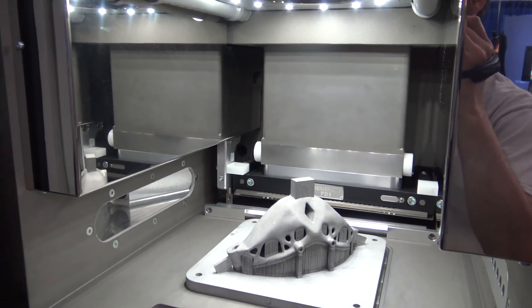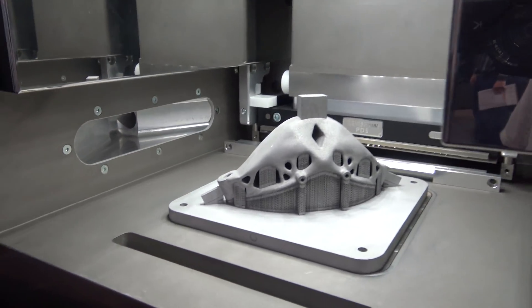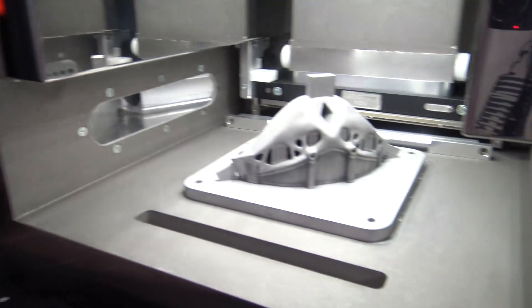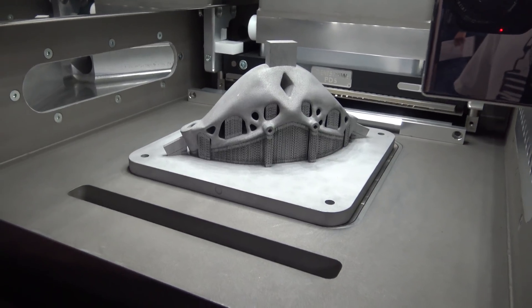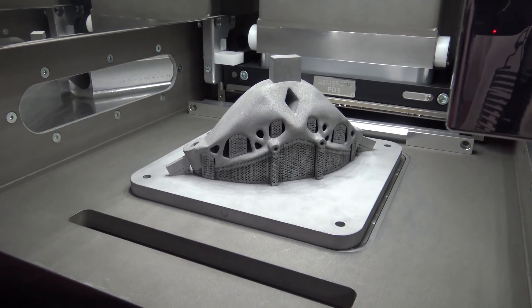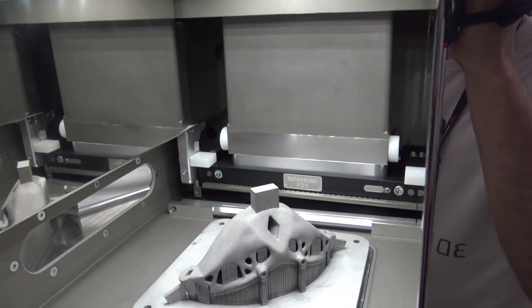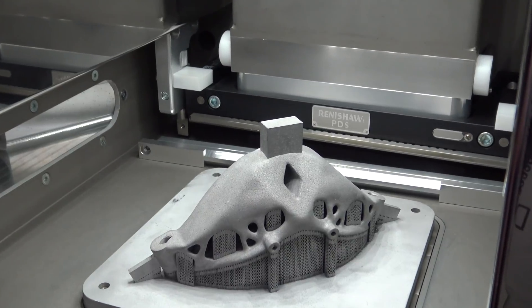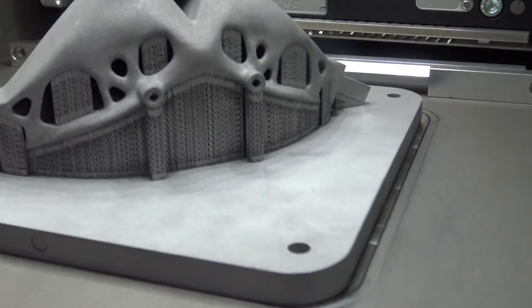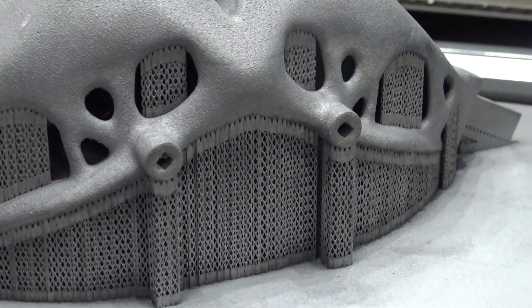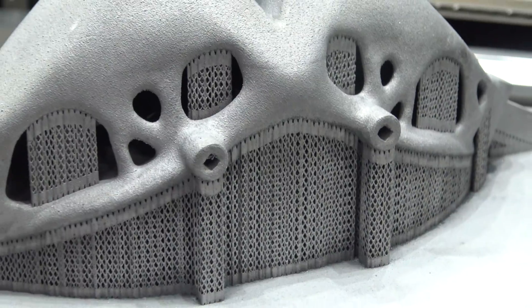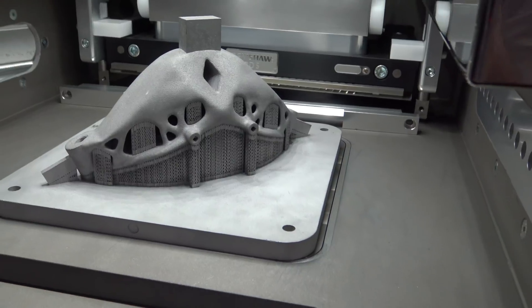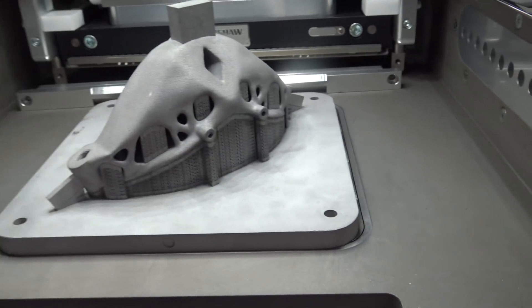What kind of post-processing is involved in something like this? It really depends what you're looking for. 95% of the parts coming off one of these is going to want some form of post-processing. That could be as simple as polishing or bead blasting or sandblasting, but the majority of the time it's going to want some traditional machining. Any mating surface is going to want some traditional machining.